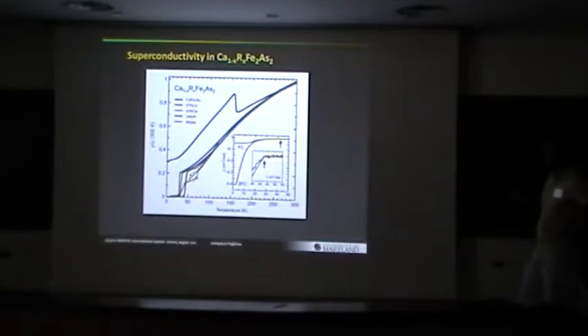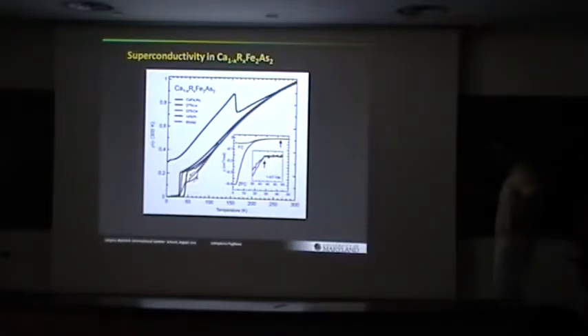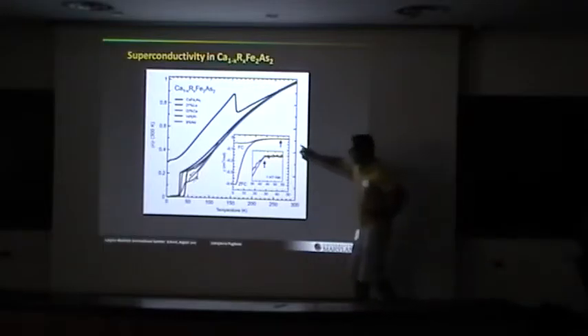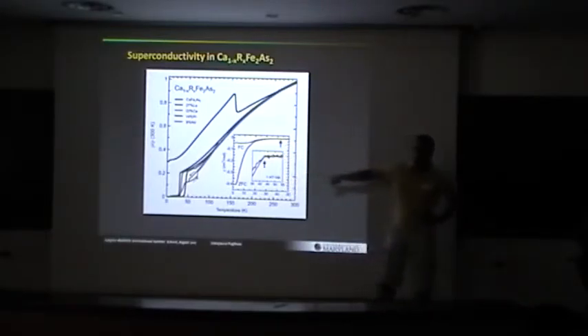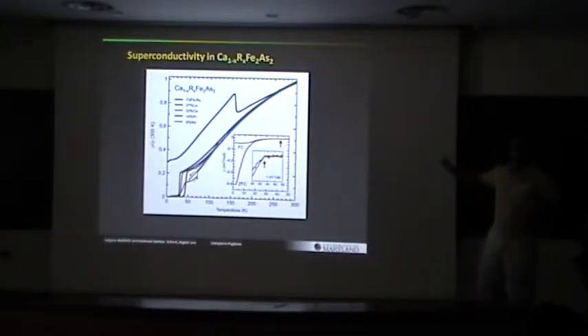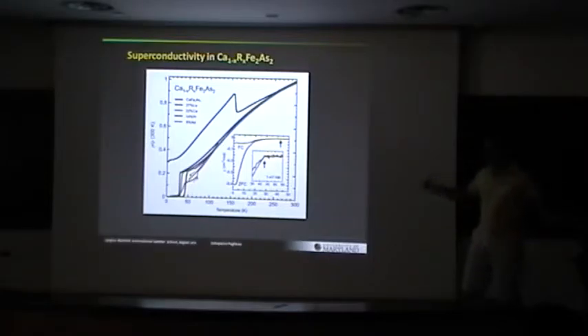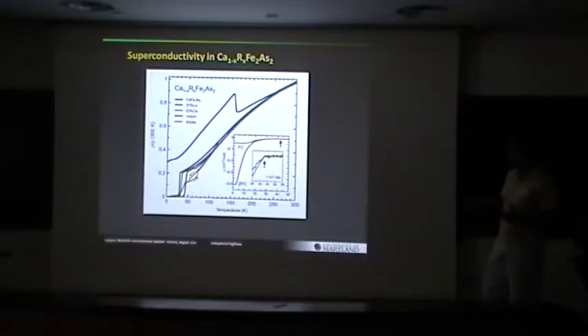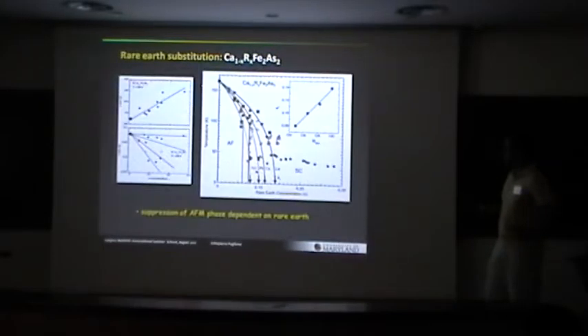First of all, to summarize some resistivity data, and here you can see a neodymium sample that very clearly shows the hysteretic behavior, and then it shows the superconducting transition. So the caveat is that the Meissner screening fraction we see here is very small. All the samples we measured, the screening fraction is small. We don't know why. We don't see good evidence of bulk superconductivity. Nevertheless, it's always showing superconductivity here. Okay, so just to wrap up,